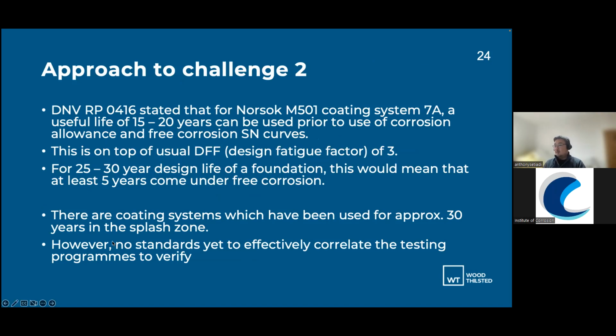So what do we do in terms of how we deal with this? We try to use at the very least something that can have the 20 years rather than 50 years. And at the moment in DNV, we have to use a glass flake system. There are potentially other products that we can use that can go beyond the 20 years. What we then do is we continue with using a design factor of 3, which is one of the highest that we can put in for offshore wind structures. And that gives us a little bit of safety factor in terms of how the structure will behave.